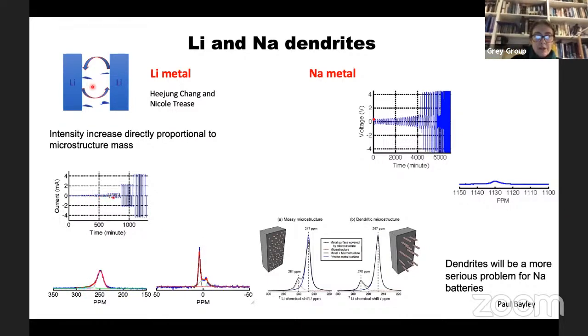So we have lithium on one side and lithium on the other. We go backwards and forwards at increasingly higher currents, with a constant mass of lithium, but you can see this is the lithium metal signal, and you can watch it grow as the surface area is increasing. Therefore, the penetration of the RF is increasing due to these dendrites. So watch the dendrite signal coming up here as you increase the current.